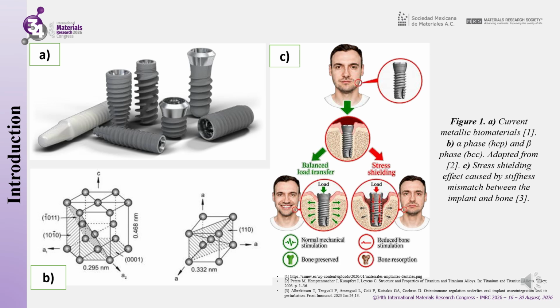The present study evaluates the wear resistance of the Titanium-25Nb16Hf with X-copper system, with copper additions from 0 to 7% by weight, a combination that has been little explored, synthesized by electric arc melting to ensure high purity and homogeneity. In order to analyze the microstructure and crystalline phases, X-ray diffraction and optical microscopy were used alongside Vickers and Knoop hardness tests, determination of Young's modulus, and tribological and surface roughness tests in accordance with established standards. The objective of this study is to establish a correlation between the microstructure influenced by copper and the wear resistance and mechanical properties of the alloy. This will enable an assessment to be made of the alloy's potential for use in bone replacement applications.